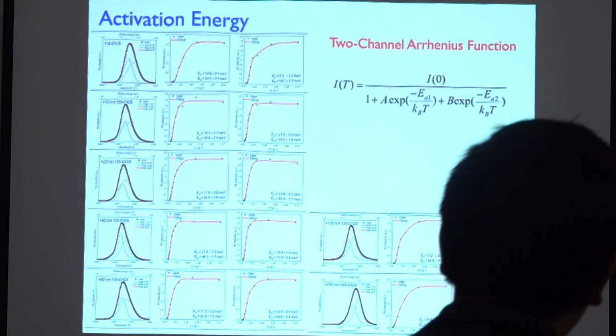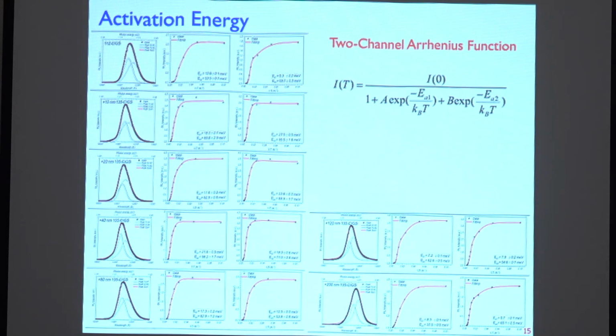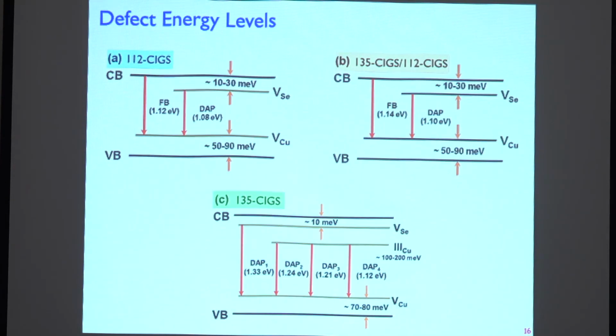And to find the activation energy, we need to use the two-channel Arrhenius equation from our PL measurement to fit for this EA1 and EA2. I0 is the intensity at 0 Kelvin, and IT is the intensity of the PL that we measure at temperature T. So A and B are the fitting parameters. By doing all the fitting, we come to the energy diagram of 112: the activation energy of 10 to 30 milli-electron volts below the conduction band is designated for selenium vacancy, and 50 to 90 meV above the valence band is the defect state for copper vacancy in this 112 material.